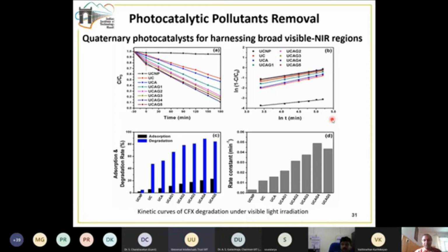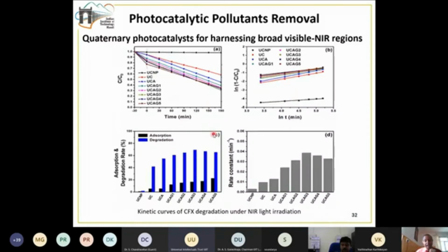So visible light, it should work. So we did the visible light experiment, and we found that one of these samples, the UCAG4, which has 4 weight % of the reduced graphene oxide, shows the best result. Then we did the NIR light experiment.